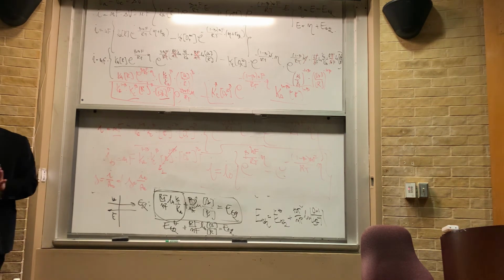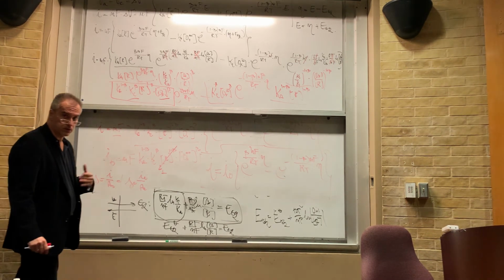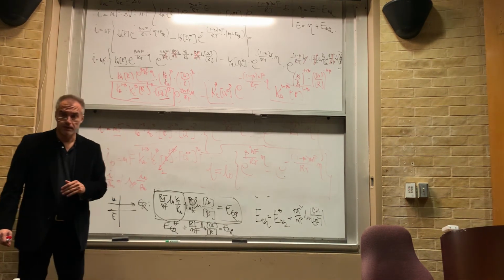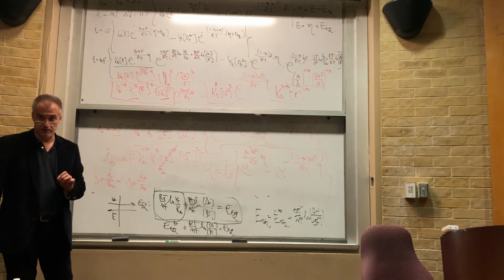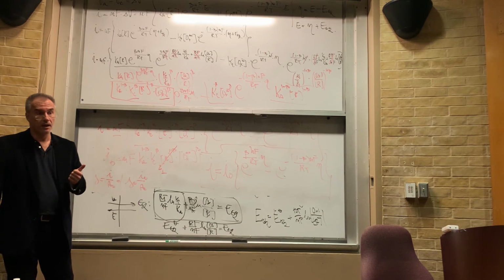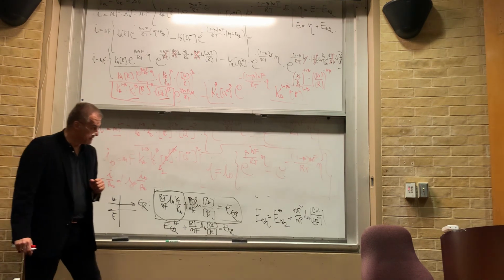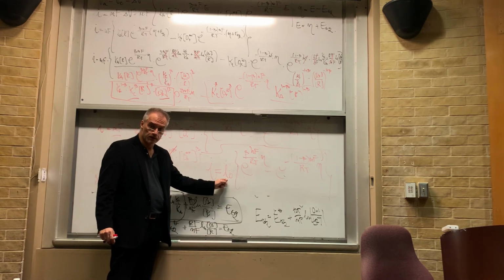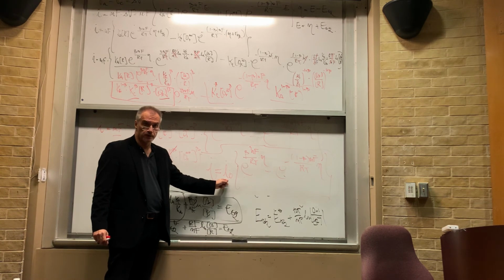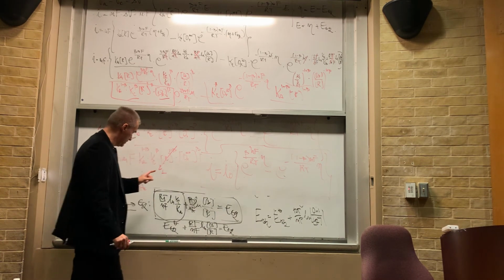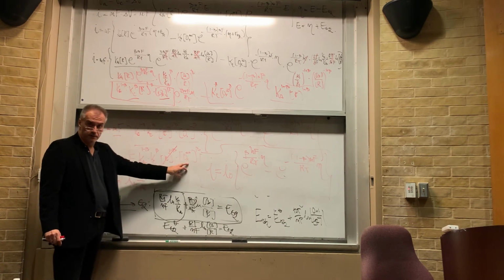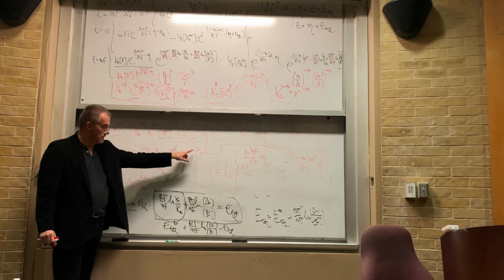If you want to get high kinetics, and we're going to talk about it during electrodeposition, it's essentially important that you have high concentration of the ions. First, to offset the transport limitations, we're going to talk about this later. But the second is to improve the value of this exponential factor, which is a function of the concentration of the ions in the solution to the power beta.